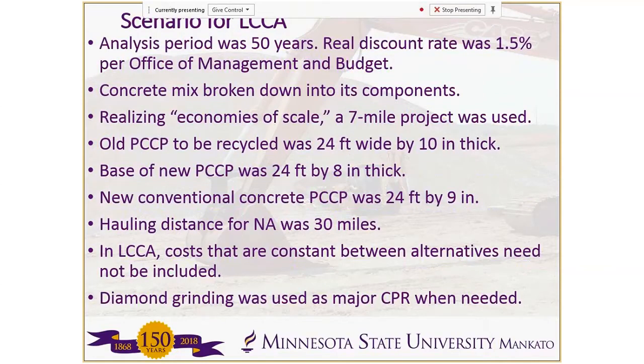So in our life cycle cost analysis that we performed, this was the basic scenario. When you do LCCA, you are supposed to assume a relatively long analysis period. So we looked at 50 years for analysis period. The real discount rate we used was 1.5%, which was the recommended value from OMB.